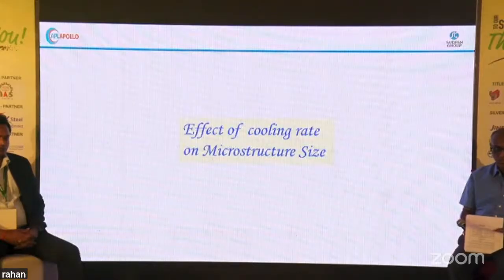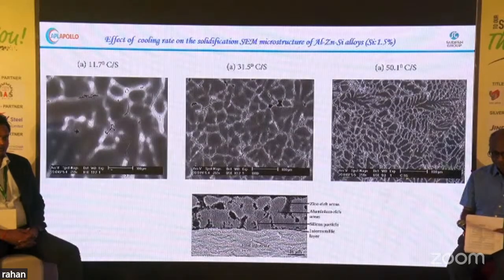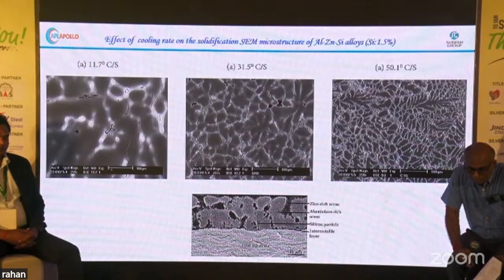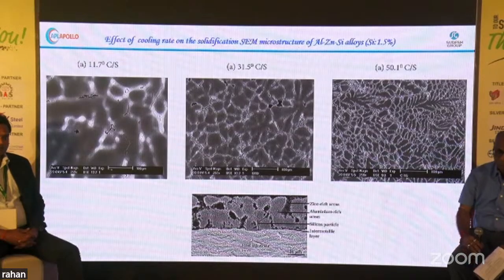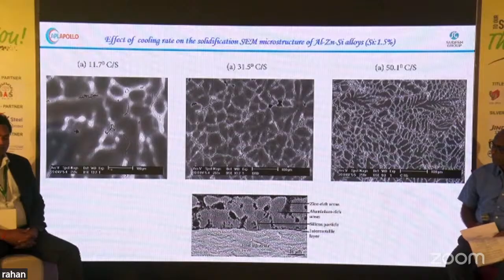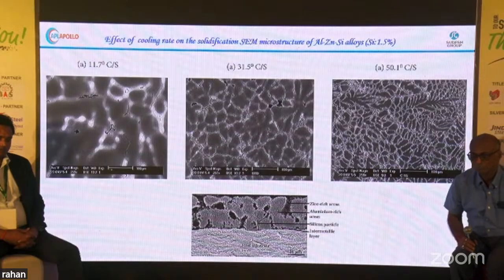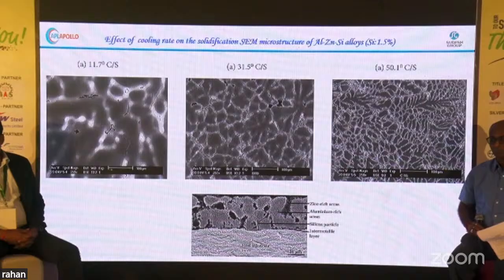Now, the second important factor is the effect of cooling rate on microstructure size. The top left cooling rate is 11 degrees Celsius per second, the middle one is 31 degrees Celsius per second, and the top right is 50 degrees Celsius per second. The bottom is the cross section in the SEM analysis. Here also we can see lots of zigzag narrow paths when we increase the cooling rate. It means there is very little time for the forming grains to grow, and when we decrease the cooling rate, small grains merge and make the grain size larger.